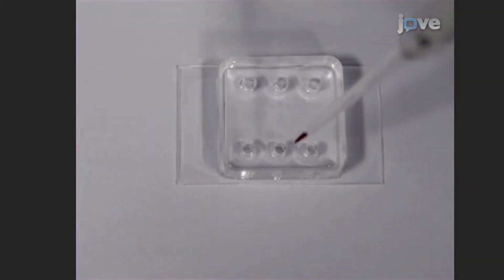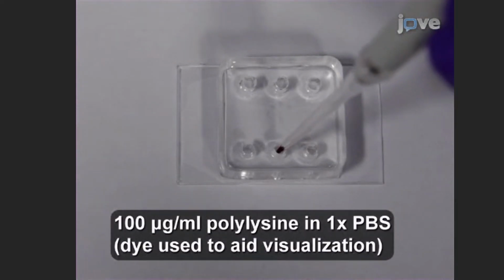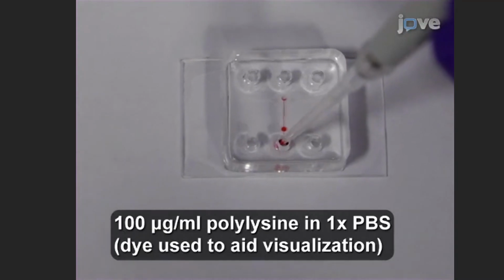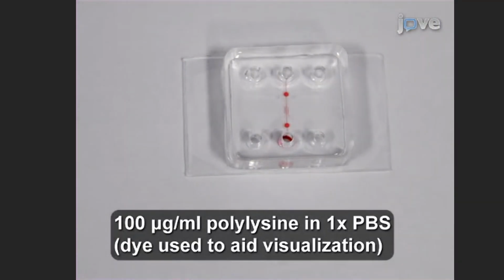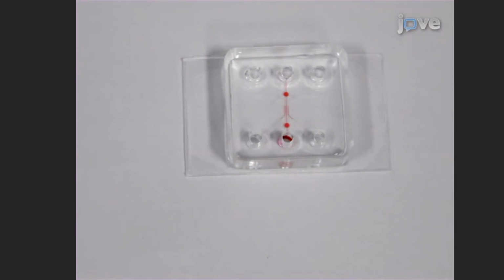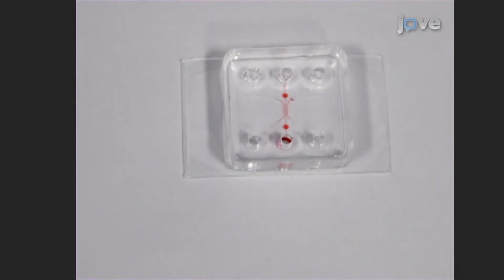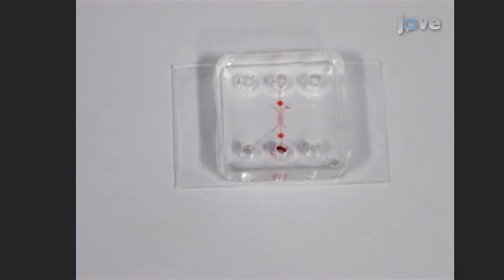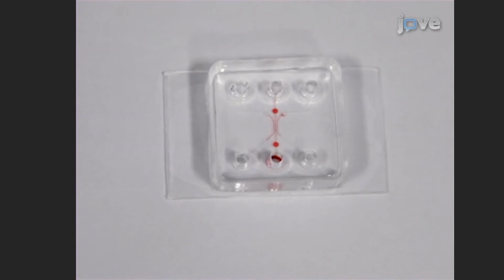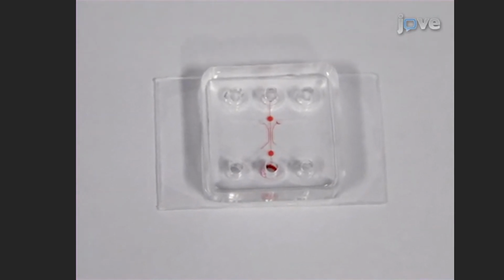Shortly after plasma bonding, pipette 0.5 microliters of polylysine into the bottom center port. The entire microfluidic circuit should be filled by capillary action within seconds. Then, leave it for a few minutes to fully coat the hydrophilic PDMS surfaces with polylysine.